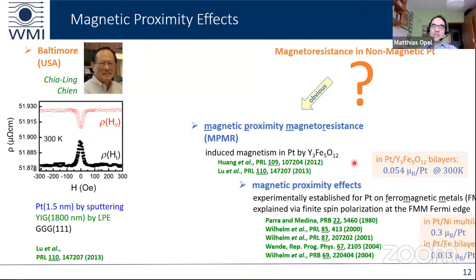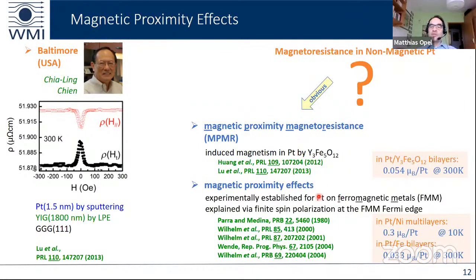Such a magnetic proximity effect is well known and well established for platinum, but not on ferromagnetic insulators like YIG, but on conventional ferromagnetic metals. So for instance, it is well known for platinum on nickel, where people found a magnetic moment of 0.3 Bohr magnetons per platinum at low temperatures. It is also well known for platinum on iron, where people found a magnetic moment of 0.033 Bohr magnetons per platinum at room temperature. To find a magnetic moment for platinum on the insulating YIG was something new at that time. And this called for a detailed investigation also in our samples.